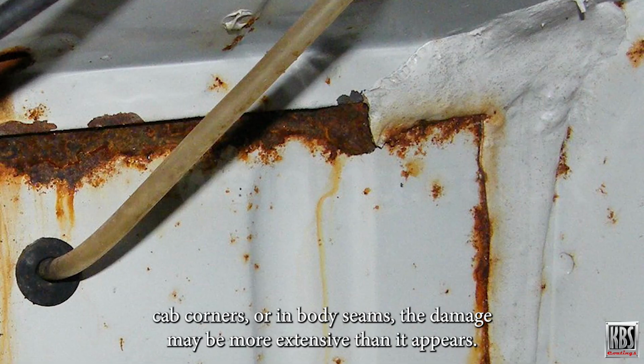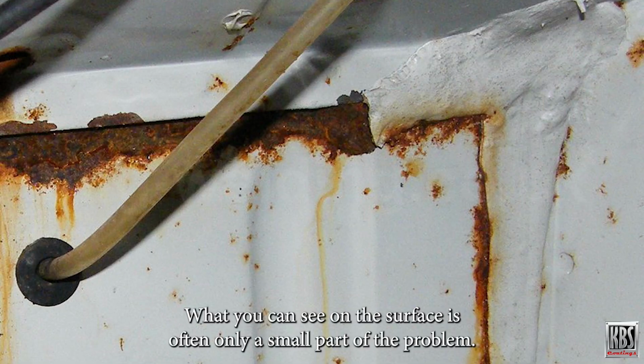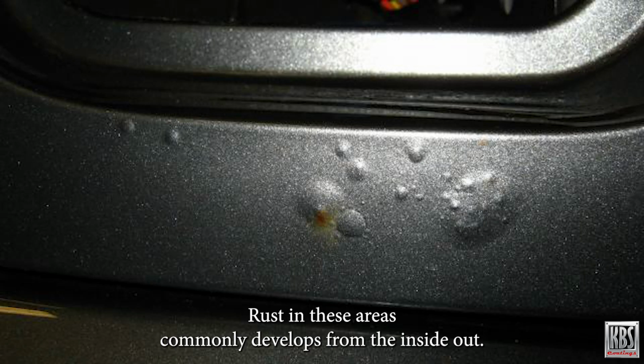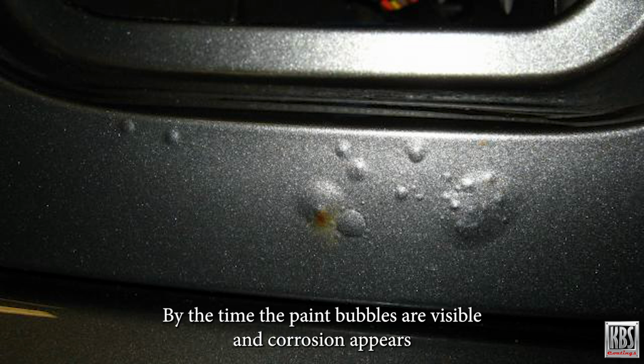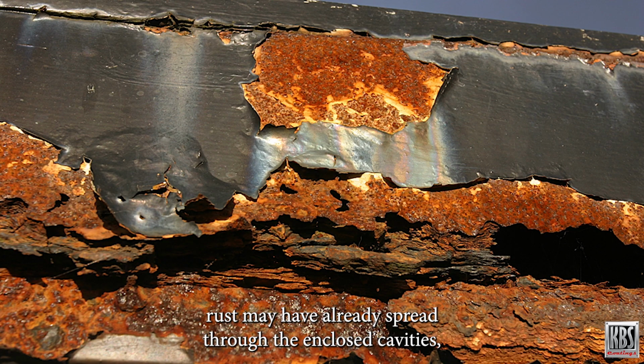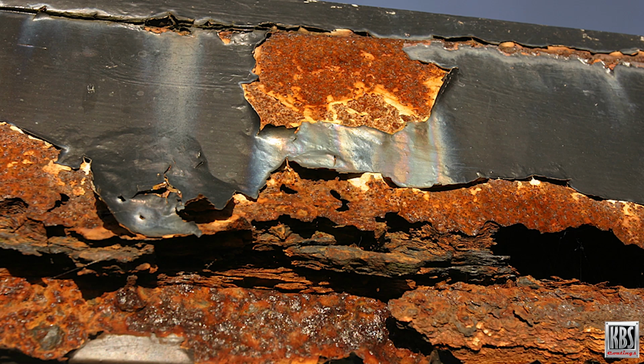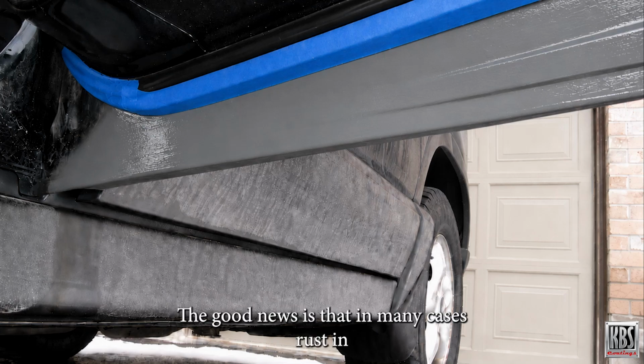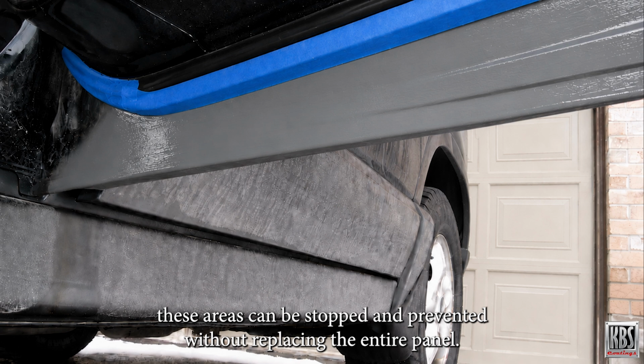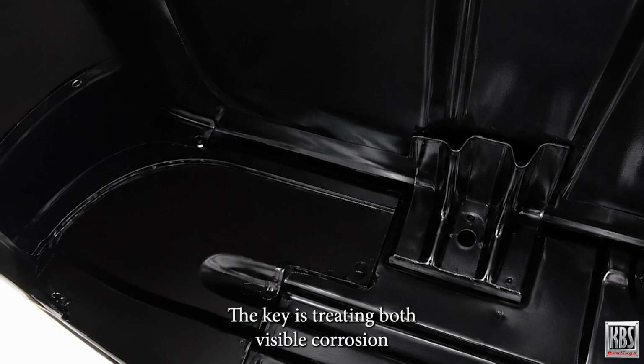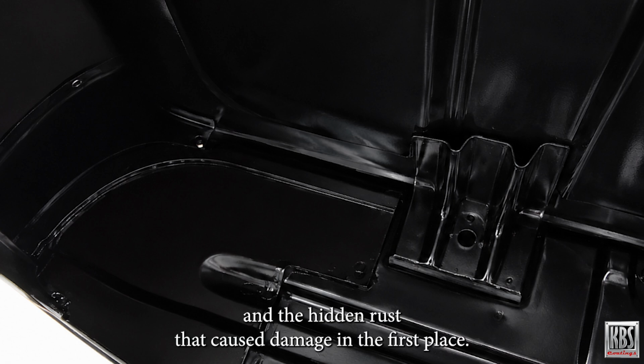more extensive than it appears. What you can see on the surface is often only a small part of the problem. Rust in these areas commonly develops from the inside out. By the time the paint bubbles or visible corrosion appears, rust may have already spread through the enclosed cavities, overlapping panels, and hidden seams. The good news is that in many cases, rust in these areas can be stopped and prevented without replacing the entire panel. The key is treating both the visible corrosion and the hidden rust that caused the damage in the first place.